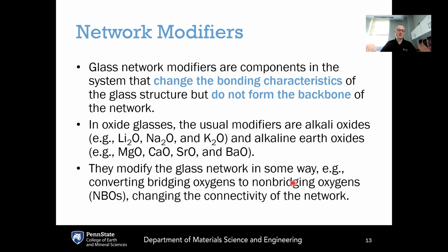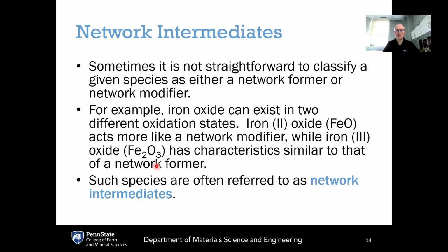This is what helps to lower the melting temperature of soda-lime silicate glass versus pure silica. The sodium and the calcium come in, they disrupt some of the bonding between neighboring tetrahedral units. So instead of having 4 of the corners of the tetrahedra shared, maybe only 3 out of the 4 of the corners are shared. This means that there's fewer bonds. This means that we can melt it at lower temperatures. The viscosity is lower, so it flows more easily at lower temperatures. But you still have enough bonds there, and still you have at least 3 of the corners shared, so you can build this 3-dimensional network.